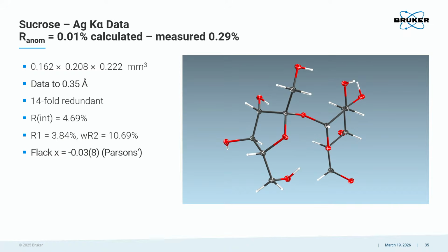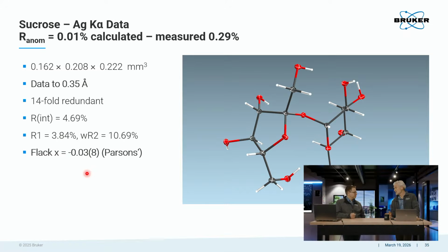That is a clearly determined absolute configuration for a sucrose, which I thought would not be possible. The flack parameter is very decent. This is data to 0.35, a very respectable R value. We were actually using these data sets to look at charge density, and we didn't go out and try to do absolute configuration. This is sort of a side effect of good data we collected.